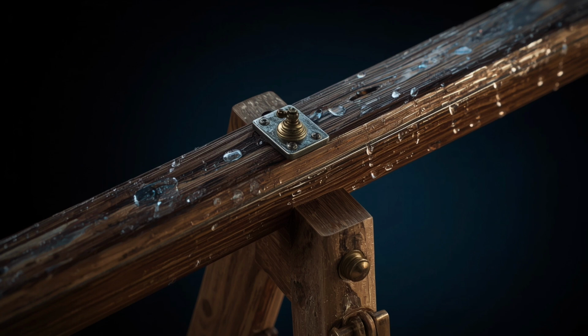During this relaxation period, the beam retained a memory of its cold temperature state, maintaining a slight geometric distortion even as temperature increased. This hysteresis extended the duration of the error beyond what thermal conditions alone would predict. These three effects, moisture-induced friction, thermal contraction altering geometry, and mechanical hysteresis delaying recovery, were each insufficient alone to create the observed error. But they didn't operate independently.